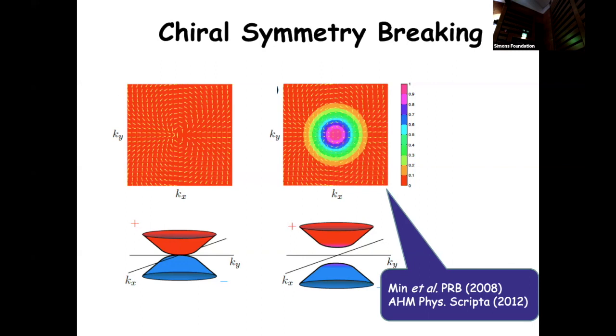The wave functions vary very, very rapidly, and it turns out exchange interactions want to heal that by basically making a vortex core in this structure, and that opens up a gap. So this is well-known physics in bilayer graphene, leads to a spin density wave state. And the basic lesson is, I'm going to make a couple of points about mean field theory calculations, which you can read as basically the DFT calculations of this subject. But when you do DFT, it's absolutely essential that you include the full non-locality of exchange, or you'll get it completely wrong.